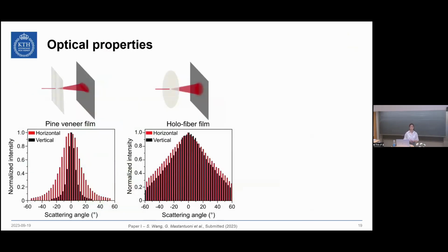This translates into different optical properties. In the case of the anisotropic materials, when we shine a laser on the structure, the light is scattered in a direction orthogonal to the fiber direction. So what we see is basically an ellipse shape in the horizontal direction. The light is preferentially scattered horizontally and not vertically. Instead, if we do the same thing with the isotropic paper, there is no preferential light scattering. Both horizontal and vertical are to the same amount.